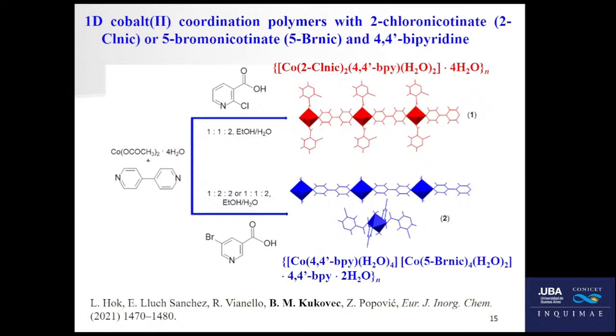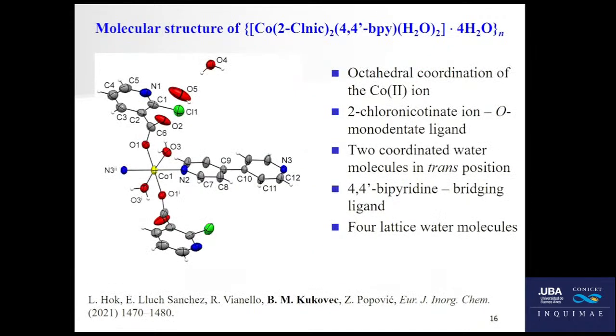Reaction conditions were quite similar, and the ratios of the reactants are given here. I'm not going to read them. We used a mixture of ethanol and water as a solvent, and the crystallization was done at atmospheric pressure, so nothing too experimentally demanding. We get two different coordination polymers. In the case of 2-chloronicotinic acid, we got this one, and the second one in the reaction with 5-bromonicotinic acid. Now we'll have a look at those compounds.